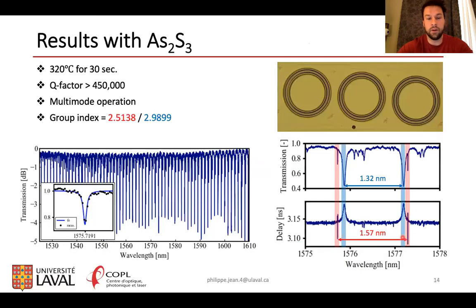So next, if we look at optical characterization of microresonators with As2S3, these were dewetted at 320 degrees for 30 seconds. And the best Q factor we measured in these was 450,000, which is equivalent to about 1 dB per centimeter propagation loss in the waveguide. And the waveguide actually supported multiple modes. And we measured group indices of 2.51 and right around 3 for these modes.